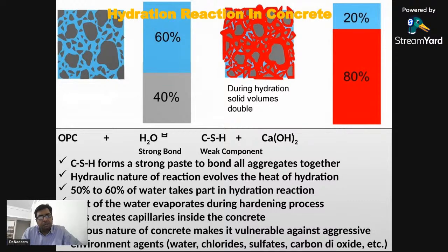Now 50 to 60% of the water, whatever water we add, say a water cement ratio of 0.3, 0.35, 0.4, or in high grade concrete nowadays we are using a water cement ratio of say 0.2 also. So 50 to 60% of the water only takes part in the hydration reaction. The rest of the water gets evaporated, which creates a lot of capillary pores, which we need to address. If we want concrete to last long, say a 100 plus year service life, then we need to address those issues, which we'll discuss in subsequent slides.